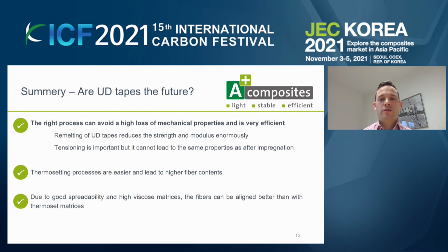If you have to remelt the material, like for organosheet production or for complex shapes in injection molding processes, for example, you have to keep in mind that there are tremendous decreases of modulus and strength. And also you have to keep in mind that the tensioning of the tape and the part is very important, but it's very difficult for injection molding processes. If you now compare the thermoplastic route with the thermoset route, then it can be clearly stated that it's easier to use the thermoset process route, which leads to a higher fiber content than for thermoplastics.